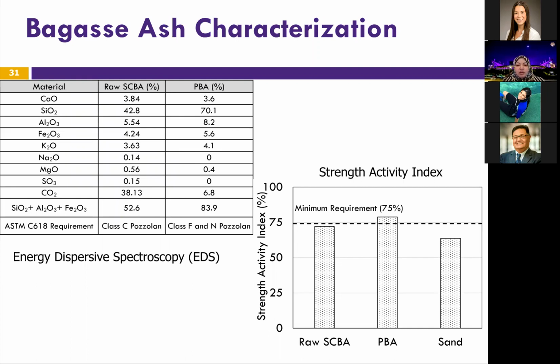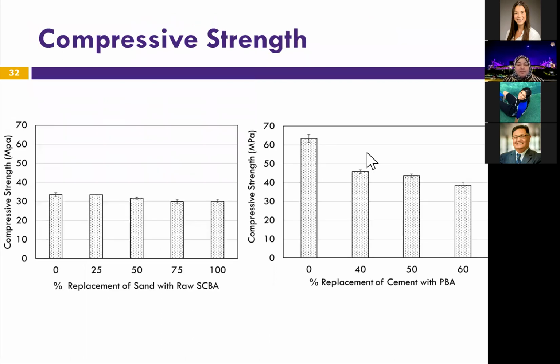The chart on the bottom side shows the strength activity index. As you can see from here, the processed bagasse ash met the minimum requirement, which is 75%. So it is suitable for being a replacement for the cement.